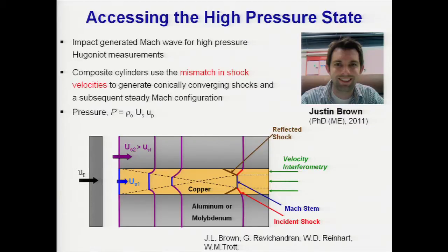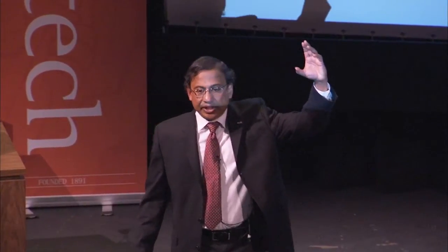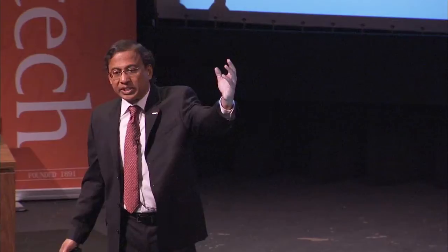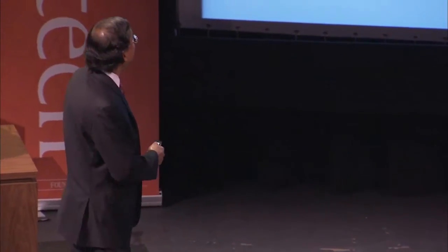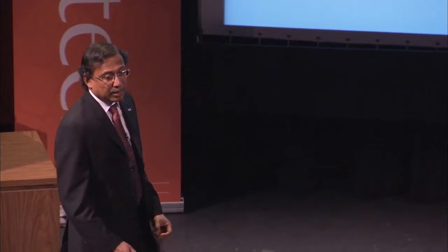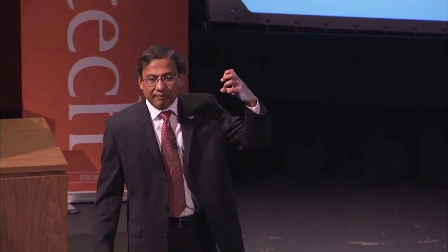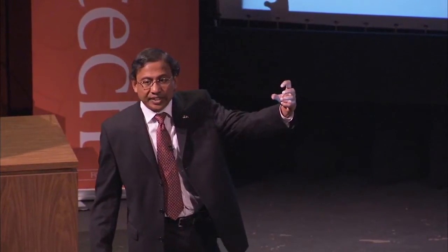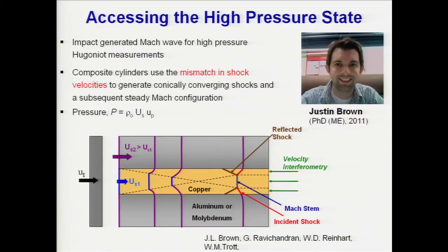And here, the idea is this. If you want to achieve very high pressures, you can increase the impact velocity. If you increase the impact velocity, you increase the particle velocity, and then you can achieve high pressures. But we are limited by the impact velocity of the facility which we have, and the impact velocity in our case is about 2 kilometers per second.